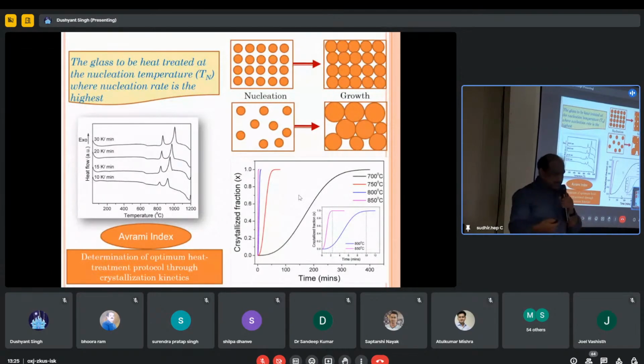So how do we do it? You have to ensure a large number of nuclei are formed in the glass matrix. If you have a large number of nuclei, then the crystals will grow to a very small size and be uniformly distributed throughout the matrix. But if you have only fewer crystals like this, then your crystals will be much bigger and of dissimilar size, and the mechanical property will not be strong.